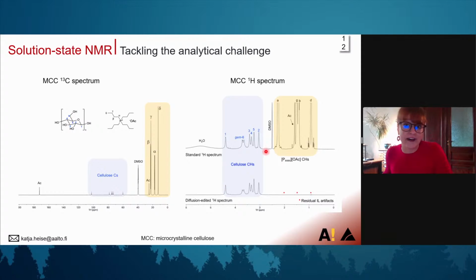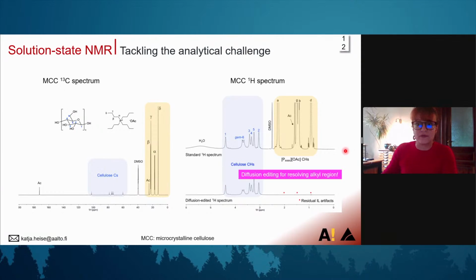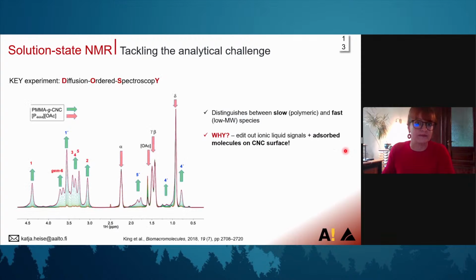However, if you now modify, for example, with alkyl chains on the surface, you might need to get rid of these ionic liquid signals because, of course, they're overlapping with what we actually want to observe. And this is when one technique that is also a key technique for our experiments comes into play, which is diffusion editing, to resolve, for example, the alkyl region. And it's an experiment that is based on diffusion coefficients. So it's diffusion ordered spectroscopy, or DOSY.